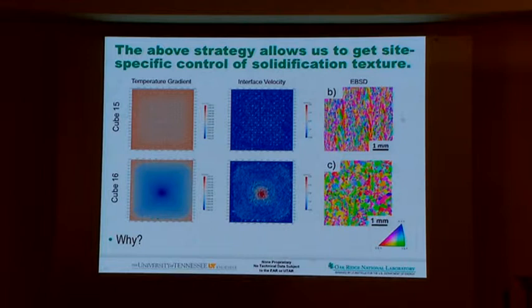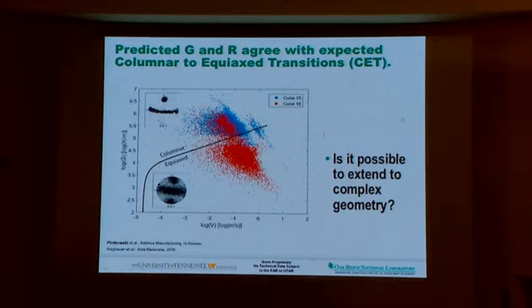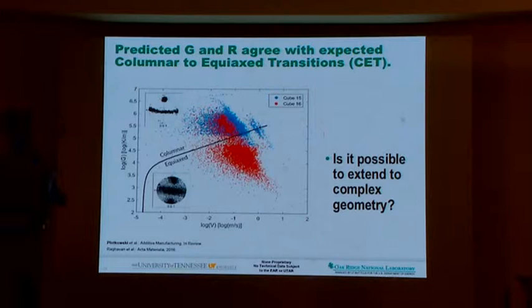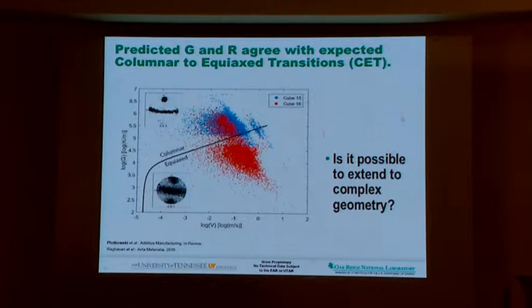So the reason why that happens is clear. You can actually do this modeling, and that work clearly shows the cube 16. Most of the data points actually lie below the equiaxed grain structure line, whereas cube 15 sits on the blue area, which is columnar structure. So now you can see how modeling is allowing us to come up with different scan strategies to figure out how to control the microstructure.